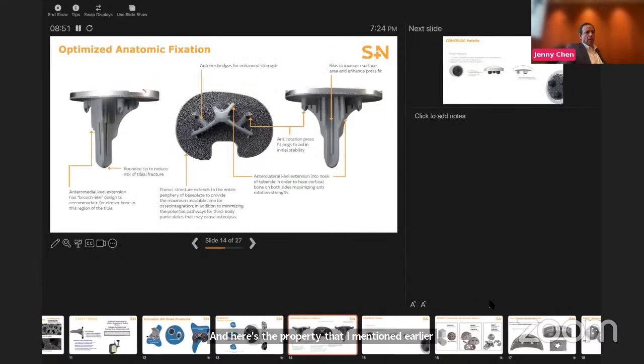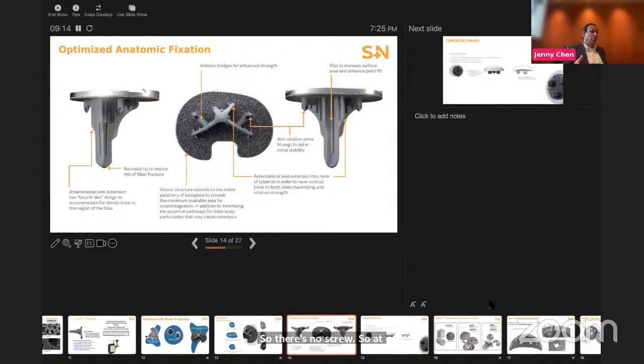A little bit closer look. As I said earlier, I grew up in the industry where the surgeons just put screws in the base plate. Well, those were no longer going to be something that the surgeons wanted, because that would be what we call osteolysis tracts, and loosening. The base plate would loosen over time as the polyethylene would wear into the base plate. So there were no screws. So at surgery at T = 0, that base plate had to be very solid. So we get a press fit.